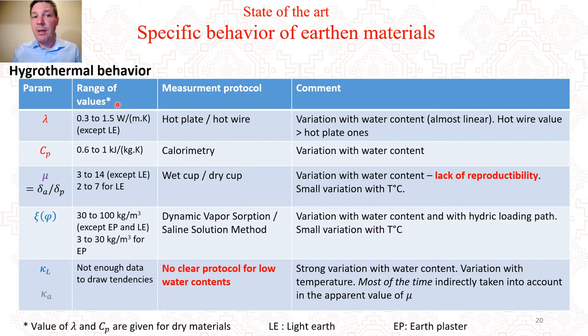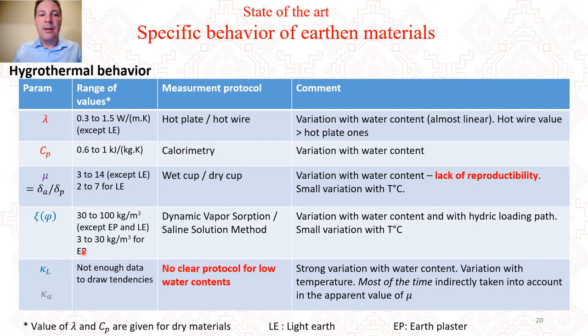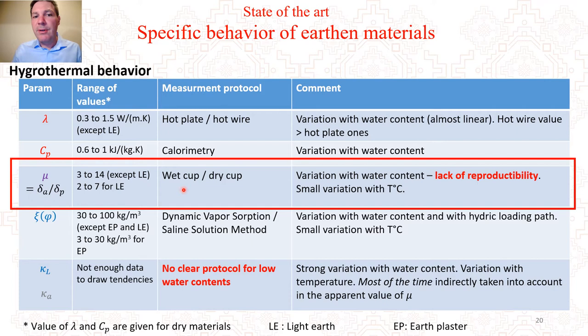This parameter is very important, even if we do not consider light earth insulation materials — for quite dense earth materials we can have a quite important range of values. The second point is that there is no clear protocol for some parameters like the effective vapour diffusivity coefficient when the water content becomes too low. For the µ value, which is quite important, even though a classical test exists to measure it, round-robin tests between laboratories show a strong problem with the wet-cup and dry-cup measurements, with a strong lack of reproducibility. That is why one of the actions of the round-robin tests in the TC was to study this parameter in particular.